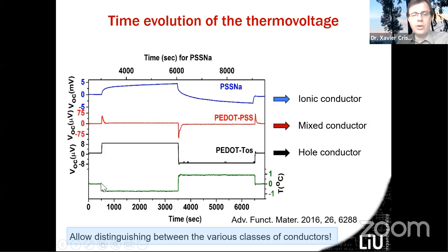So for instance, if you apply -1 degree, for the pure electronic conductor, these hole conductors, what you see is a direct small increase of potential here, like something like 8 microvolts.